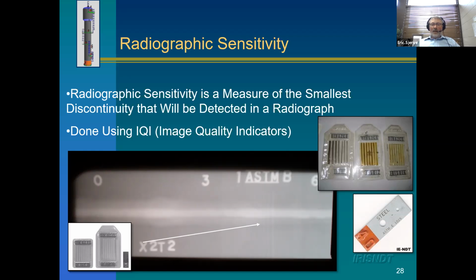Typically with radiography, we want to be 2% sensitive. So if our plate is 100 millimeters thick, the minimum variation in thickness we want to see is 2 millimeters. That's what those wires do. We put those wires over the weld, just like in that picture at the bottom, and we need to be able to see roughly a 2% sensitivity. That makes sure we've got the right sensitivity, so we're sensitive to things that are a problem, and we're insensitive to things that are so small they're never going to cause a problem.